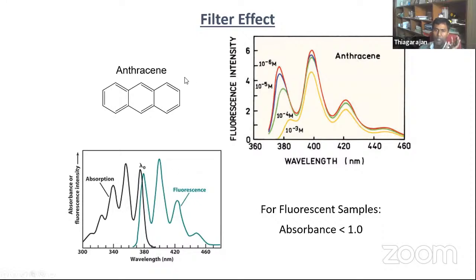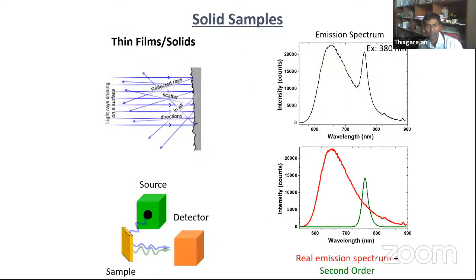For example, for anthracene molecules, a very low concentration is micromolar. Here you see it in millimolar. Even though we have a lot of molecules in the solution, the emission intensity of the millimolar anthracene solution is lower than that of the micromolar solution. So it's better to always keep the absorbance lower than 1 in order to avoid the inner filter effect.